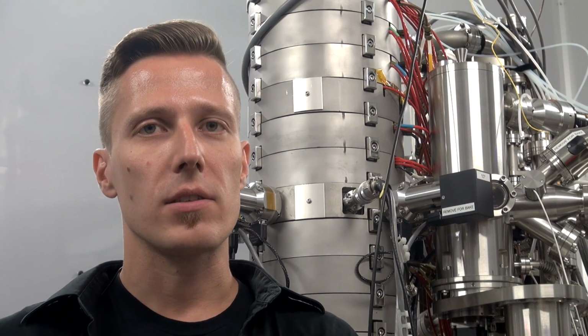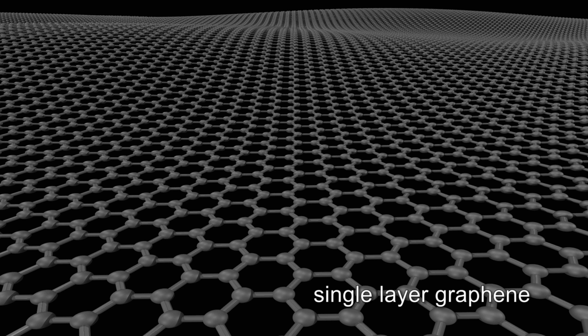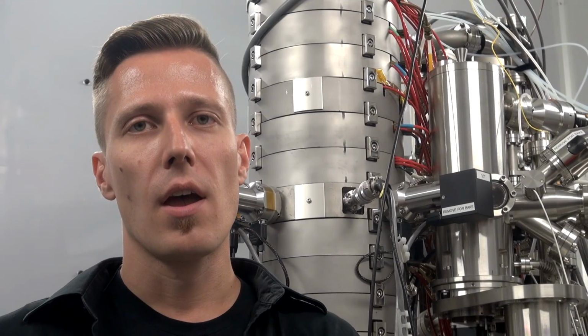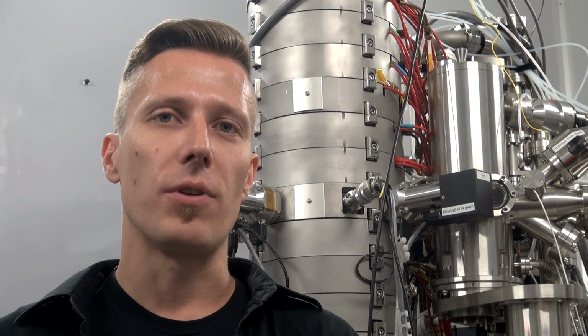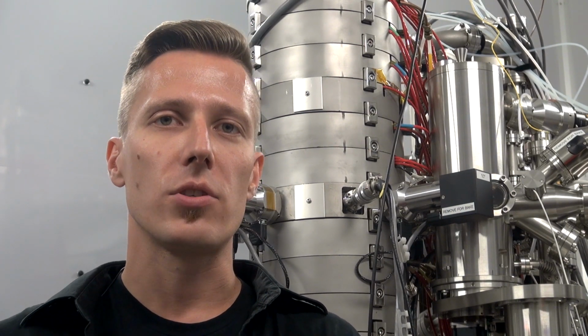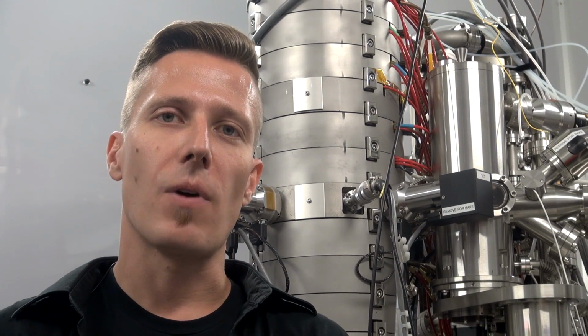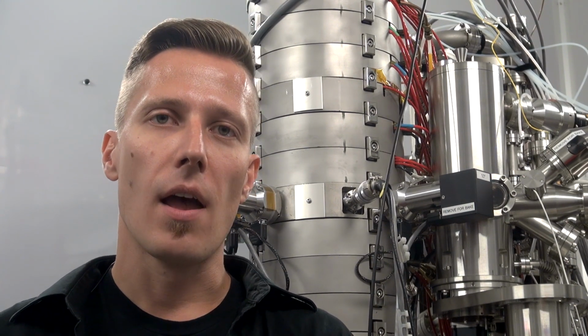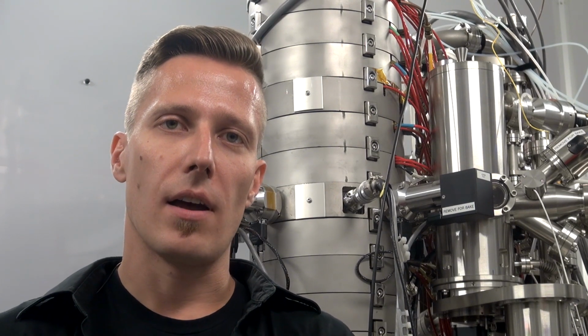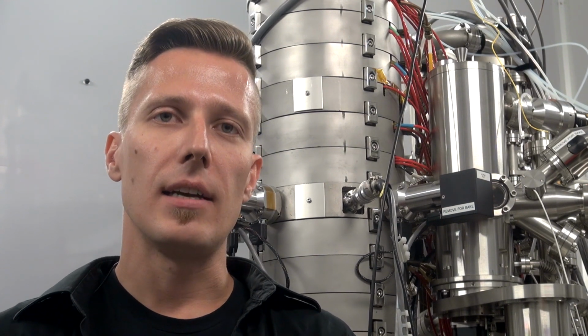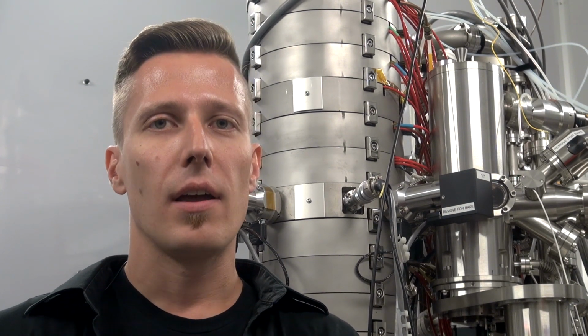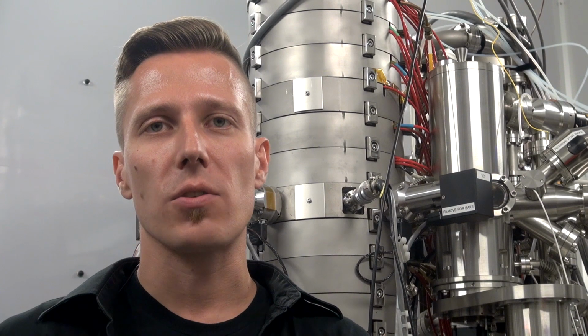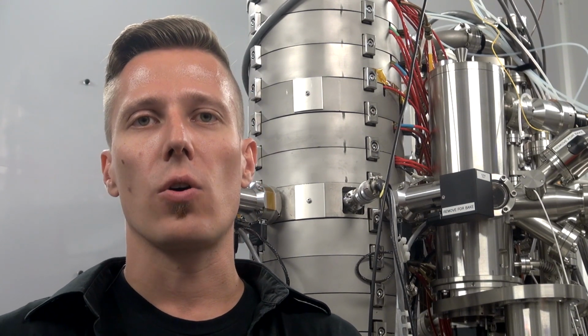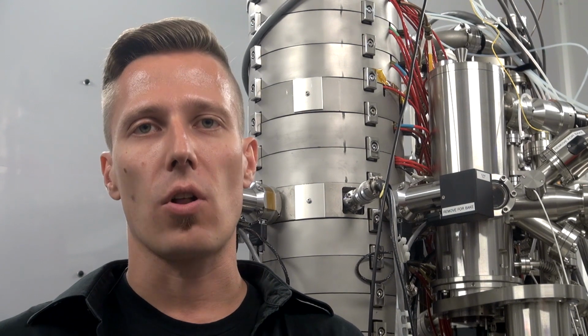For these kinds of studies, graphene, the one atom thick sheet of carbon, is really the best material. So it's not surprising that many people, including our collaborators in the UK and here at the University of Vienna, have been studying graphene by electron microscopy for several years. But in most of these studies, the material has been somehow defected, with some atoms missing. Indeed, when you use electrons to probe materials, you have to accelerate them to energies of tens to hundreds of kiloelectron volts, and they can actually cause damage in the material under study. This is called knock-on damage.